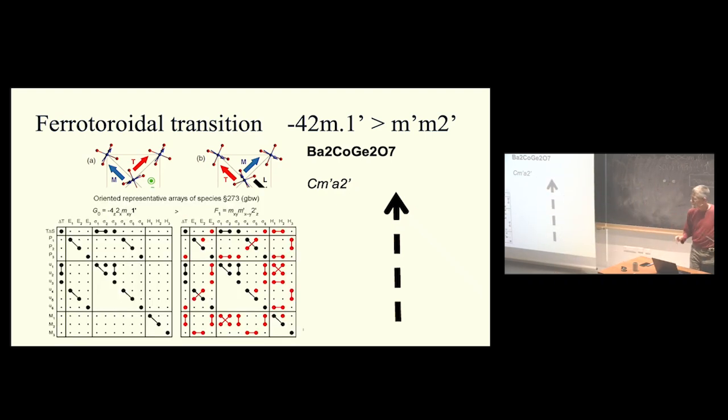So if you look at the matrix, here it is extended also with the magnetic moment. So here we distinguish the magnetic symmetry. The point group symmetry has also these dashes, which Mael was introducing. And again, you see that there is a magnetic moment allowed in the low temperature phase, and it has the X and Y components the same. So it means it looks in this diagonal direction. Then you can see here the electric field or polarization. The first component is allowed, so polarization is like this.